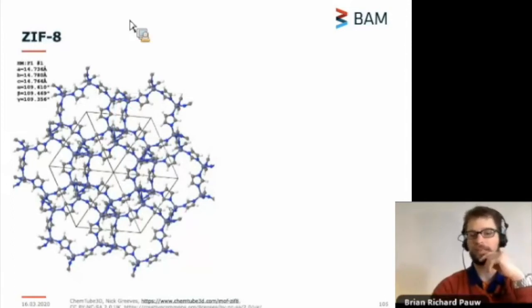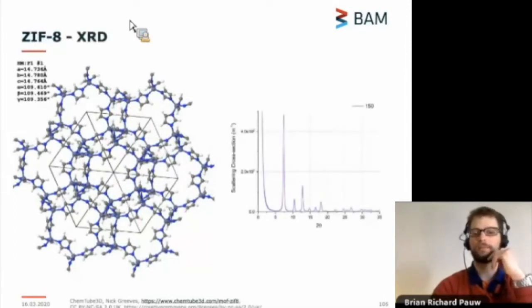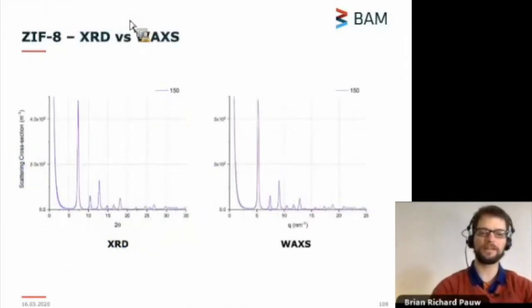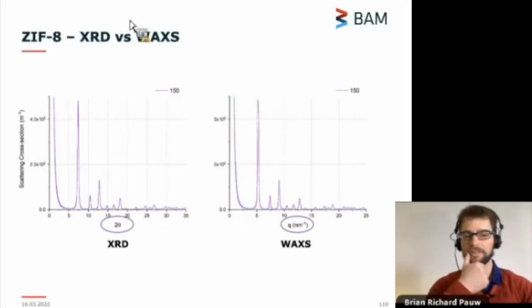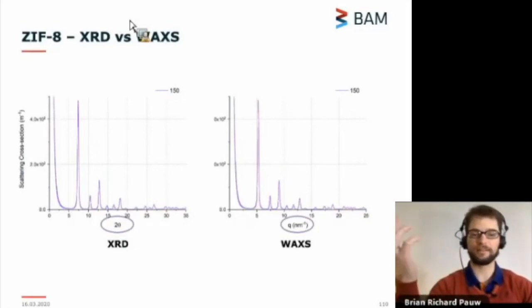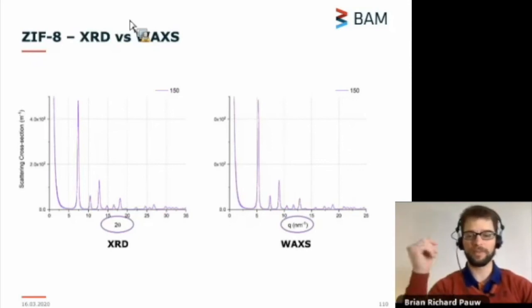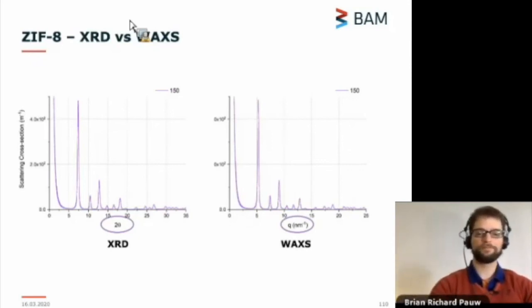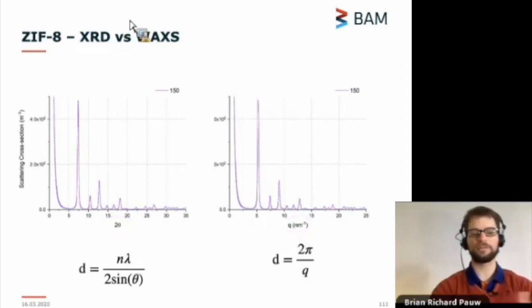And many of you will be familiar with X-ray diffraction, where you characterize these regular distances. So are these things the same? Why do we call it wide-angle scattering instead of X-ray diffraction? Well, these things are pretty much the same, but there is one crucial difference. The difference lies in the axes. With XRD, you typically measure things as scattering or diffraction in 2 theta, whereas we put things in a unit of Q. The big difference is that Q is independent of wavelength. That means that if you want to calculate your d spacings, things get a lot easier.